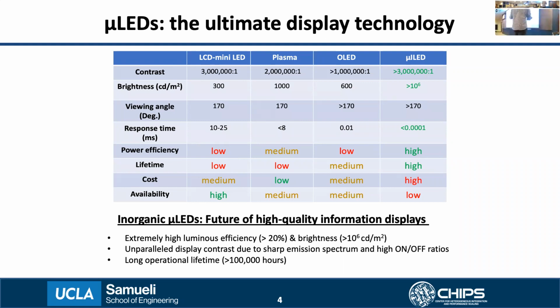These micro-LEDs are made of inorganic compound semiconductor materials such as gallium nitride or indium phosphide. Because of the crystalline nature of these materials, the electron mobility is very high. Because of this, these devices have very fast response times in the nanosecond range. Also, because these are inorganic crystals, they can be operated at much higher currents and for a very long duration of time.